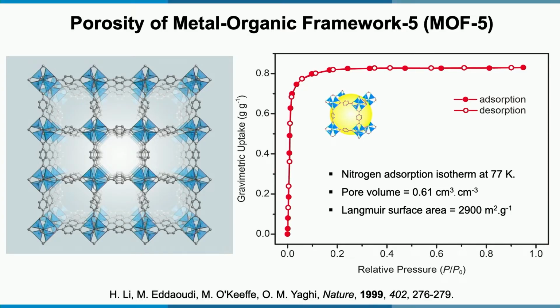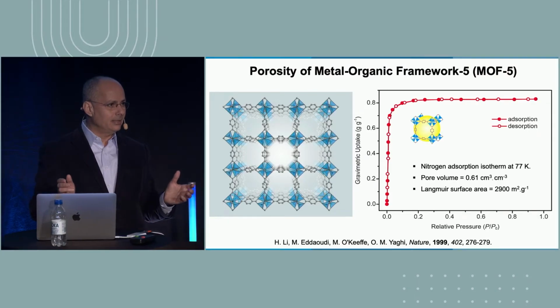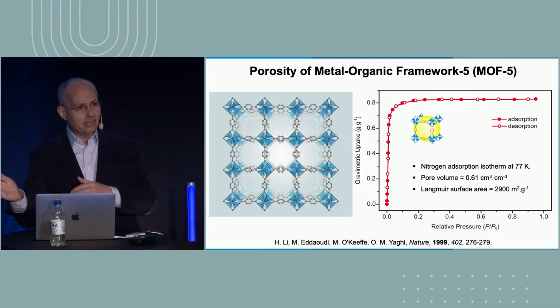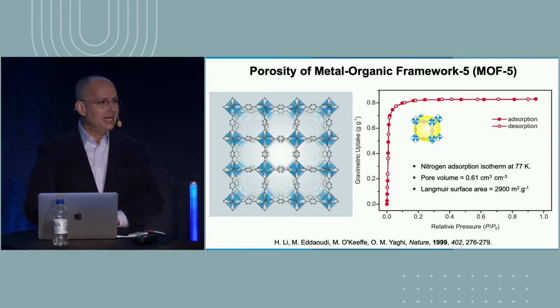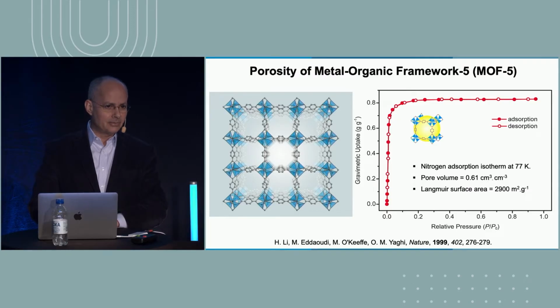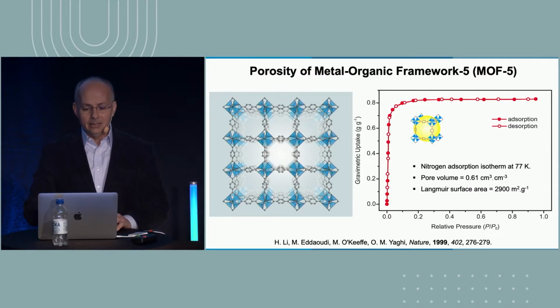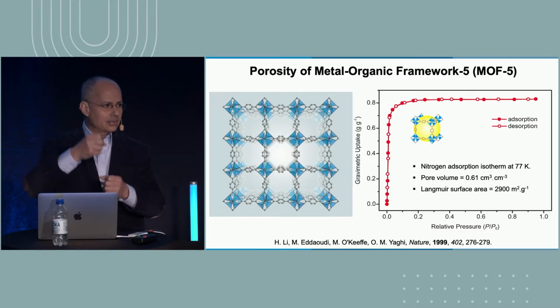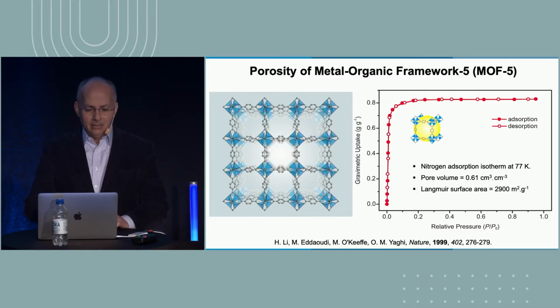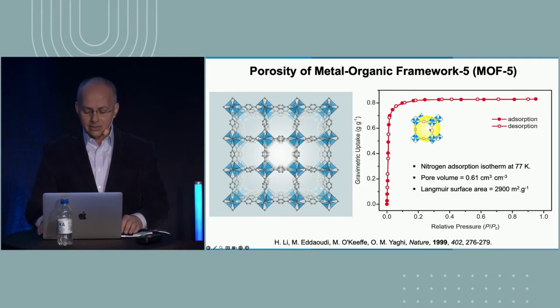So that means that in the absence of any stuffing in the pore, the structure remains open. This was truly powerful because up until this point, all porous materials like zeolites were inorganic. Or they were porous carbon, but porous carbon is not crystalline, and you can't really functionalize it because it's made of carbon. There's no CH bonds. But here, we had plenty of CH bonds, and we could use not just this dicarboxylate, but even longer dicarboxylates, or functionalize this phenylene unit, to make functionalized pores.